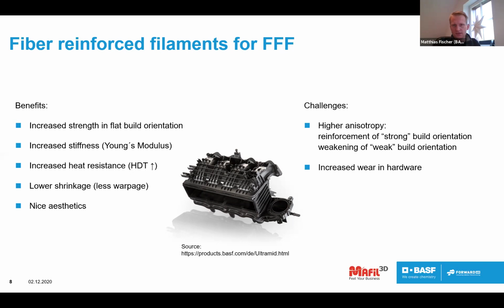Whenever you have the chance to heat the chamber of the printer, or you can close it with a cover to increase the environmental temperature of the build environment, you can reduce this effect, but in general, it's still there. So that's of course one of the challenges you need to take into account when you are working with fiber reinforced products. And also increased wear in the hardware is visible. It means you should usually use hardened nozzles, and make sure that the printer has driving gears, for example, which are suitable for these kinds of abrasion critical products.